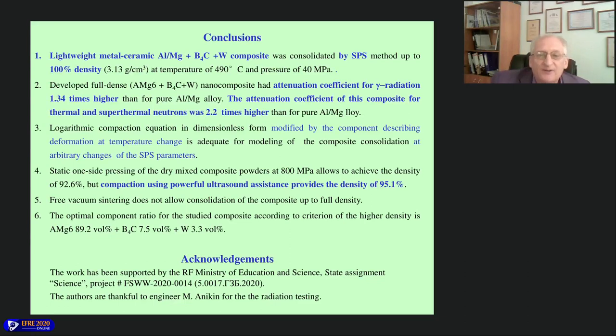at 800 megapascal allows achieving a density of around 93%. But compaction using powerful ultrasound assistance provides a density of more than 95%. It was higher than for the hot extrusion method, just pressing using powerful ultrasound assistance. But this is a special approach. It takes additional time to show such results. Free vacuum sintering doesn't allow consolidation of the composite up to full density, and the optimal component ratio for the studied composite, according to the criterion of higher density, is as follows.